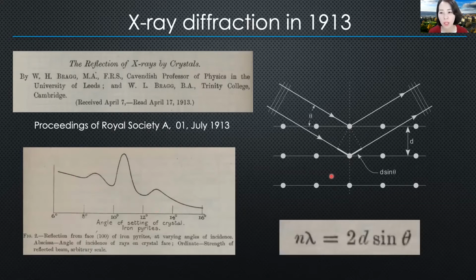If that was the case, we can introduce a single parameter d, which is the insight that we are gaining about this atomic-scale system, and use this condition to associate the peak angle, as you rotate the sample by hand, with this parameter d.